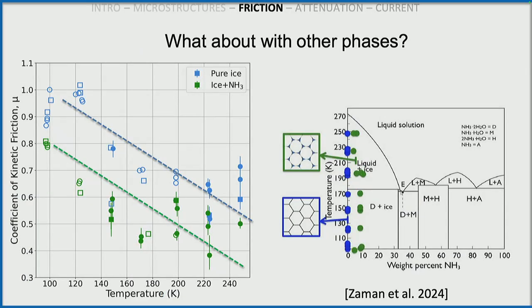But I wanted to tell you about how melt affects things. Based on that motivation of thinking about Enceladus, where its plumes were ejecting liquid water and a whole lot of other species, one of the things sampled in the geysers was ammonia. Ammonia is interesting because it has a very deep eutectic, meaning it has this antifreeze effect of about 100 degrees. And so if that was the case, then you could have melting in an icy shell much higher up in the shell than way down at the ocean interface. So he looked at the friction of both icy samples in blue and ice plus ammonia samples. And the freezing temperature is like 175.